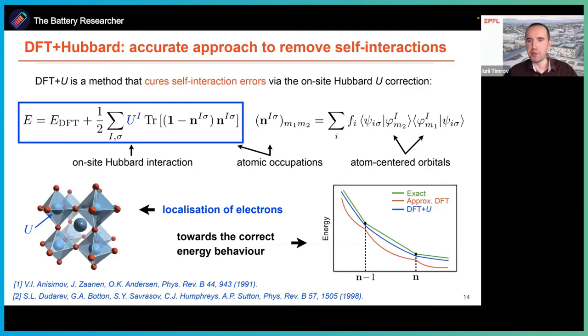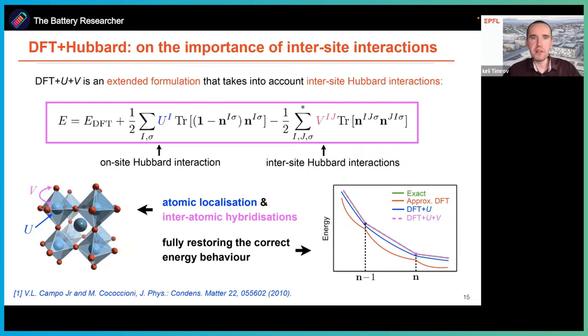There is an even more generalized or extended formulation of this correction. It's called extended DFT plus Hubbard, where we have not only the on-site correction term, but also the intersite corrective term, which now depends on another parameter, which we call V. This parameter depends on two indices, I and J. So it's really the parameter that describes the strength of the interaction between neighbors, let's say iron and neighboring oxygen. And now we are dealing also with generalized occupation matrices, which are called Nij.